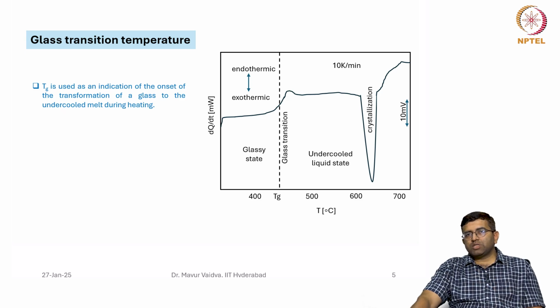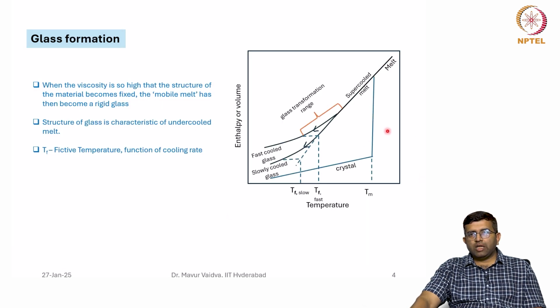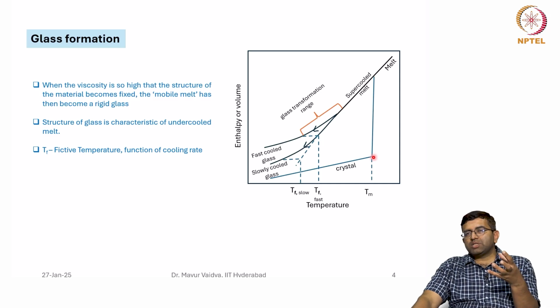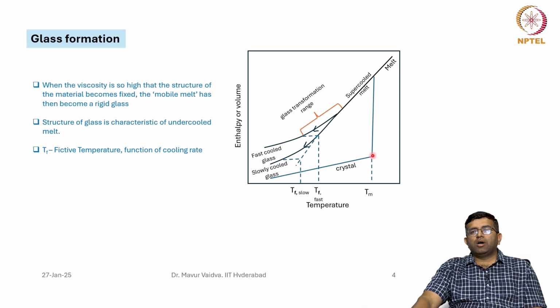This is what is known as a second order transition, and this is a first order transition. Just to tell you in very simple terms, not going into detail: when crystallization happens, there is a discontinuity in the enthalpy at the melting point. All such transitions where there is a discontinuity in the first derivative of the free energy are known as first order transitions, whereas in the glass you see that this is continuously decreasing. These are known as second order transitions.